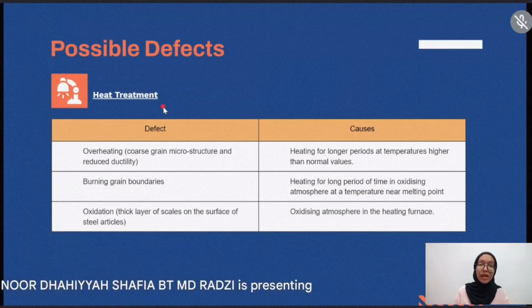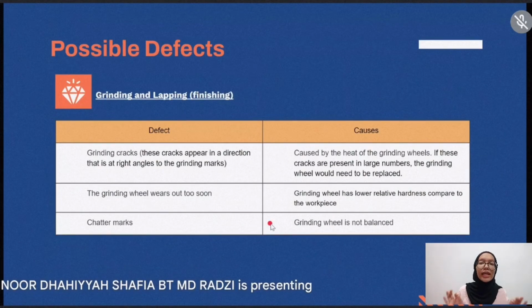In the heat treatment process, the possible defects include overheating, which is caused by heating for longer periods at high temperature. Burning of grain boundaries happens when heating for a long period of time in an oxidizing atmosphere very close to the melting point. Oxidation, which is a thick layer of scales on the surface of the workpiece, is caused by the oxidizing atmosphere in the heating furnace. For grinding and lapping, the defects include grinding cracks, which are caused by the heat produced by the grinding wheels. If the grinding wheel wears out too soon, that is because it has lower relative hardness compared to the workpiece. Lastly, chatter marks happen when the grinding wheel is not balanced.